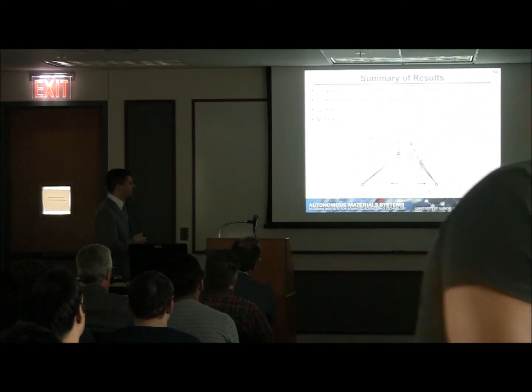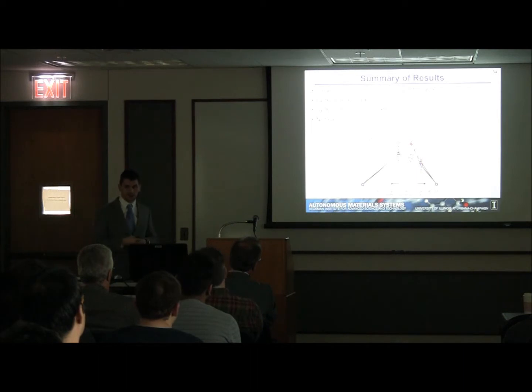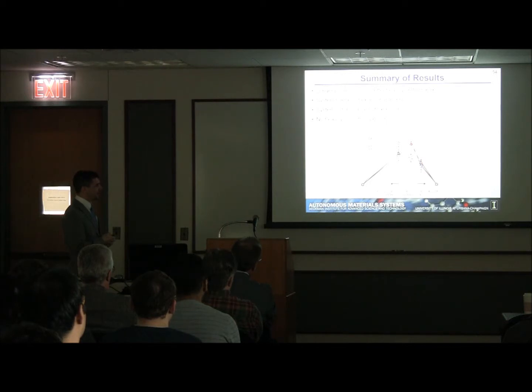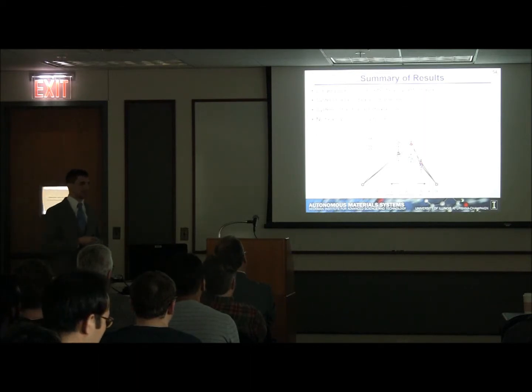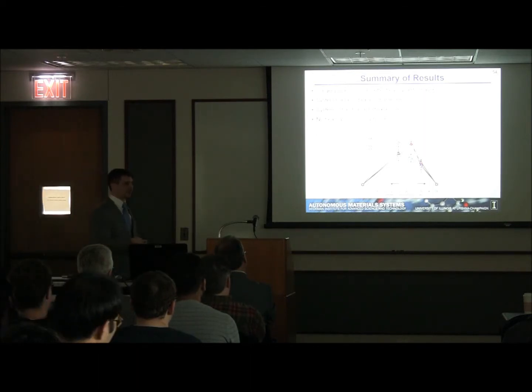Interestingly, as pulse duration went down, the healing efficiency also went down. So shorter pulses led to less healing efficiency. Also, the system was quite tolerant of excess hardener. When we had very long pulses and delivered twice the stoichiometric amount of hardener, we still had recovery of roughly 90%, which I thought was quite interesting. However, the system wasn't quite as tolerant of excess resin, and we had roughly 50% healing in the best single heal case with twice the stoichiometric amount of resin delivered.